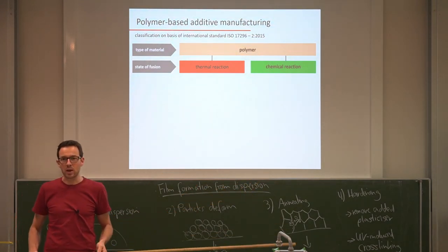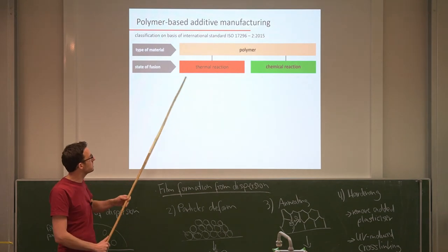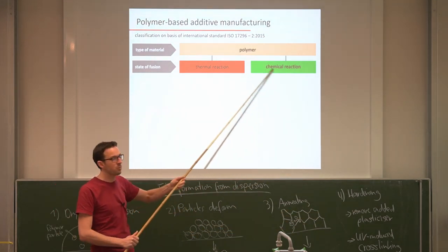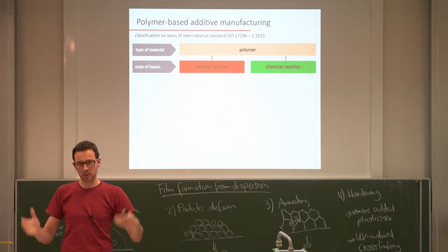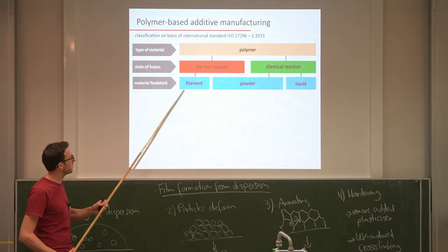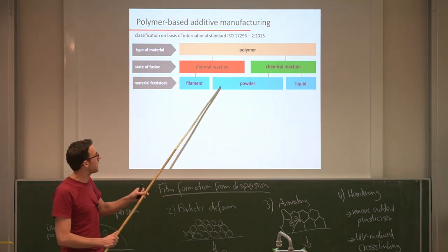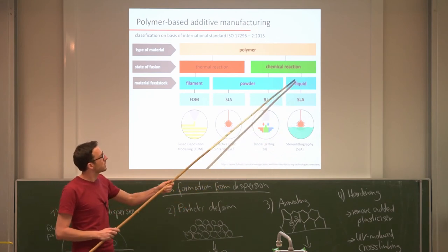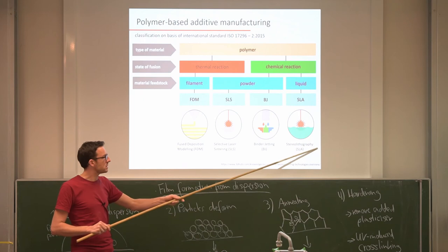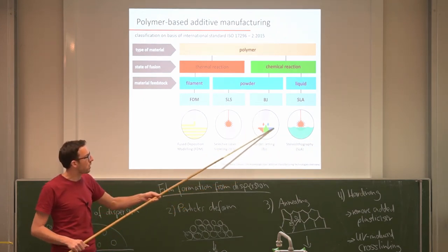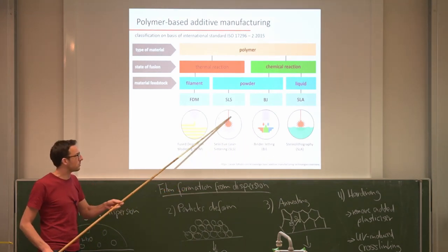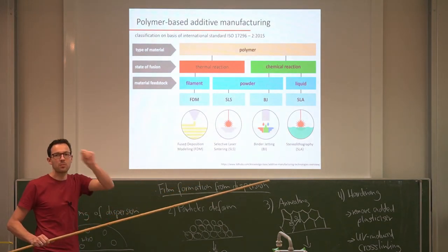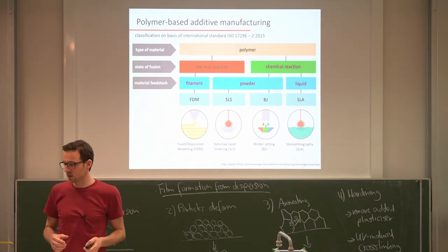Polymers are one of the key materials for 3D printing because they are so easy to reshape and mold. We can classify additive manufacturing processes by the state of fusion — how we make 2D layers and merge them into 3D objects. This can be thermal reactions — playing with the glass transition temperature — or chemical reactions. The material feedstock can be thin filaments, powders, or a polymer or monomer in liquid form. This gives rise to: stereolithography (liquid polymer polymerized by chemical reaction), binder jetting (merging polymer powder by chemical reaction), selective laser sintering (heat from a laser to sinter polymer particles), and fused deposition modeling (heating a filament and drawing the 3D object).